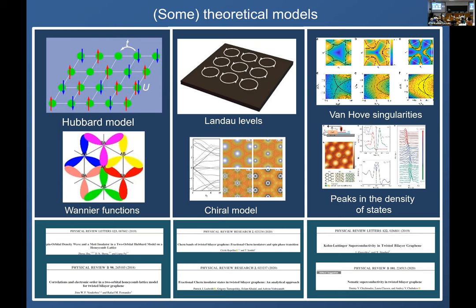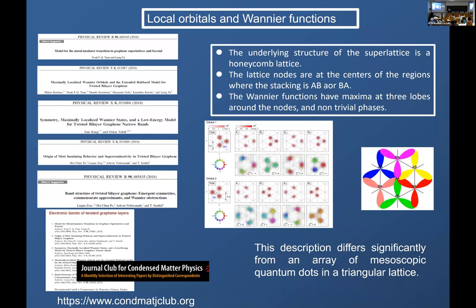The Hubbard-like picture requires first the knowledge of the Wannier functions, which is a quite challenging task. People have used the chiral model and extensions and exploited it in order to show similarities with Landau levels, which is the other clear case of flat bands in condensed matter. And then in two dimensions the density of states diverges—that of course can enhance the role of interactions. There are the van Hove singularities, and these van Hove singularities also are expected to play a major role on what happens in the phase diagram.